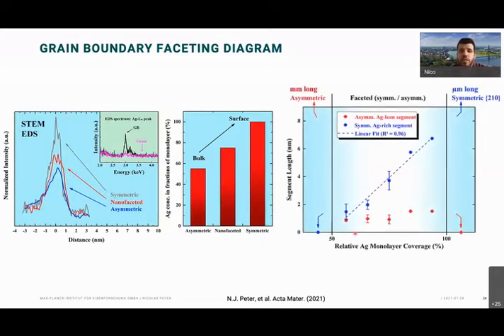So what we could also observe then is, I said one segment is growing, the other one is not. So we could establish a faceting diagram where we say, well, at a given value, we have an asymmetric millimeter long boundary, but no symmetric portions. And after this transition, we start having a more or less 1-to-1 ratio between the two facet segments. And with increasing silver at the boundary, we linearly increase the length of one facet segment, the silver containing one, until we have a micrometer long symmetric boundary towards the surface and no longer an asymmetric segment at all.